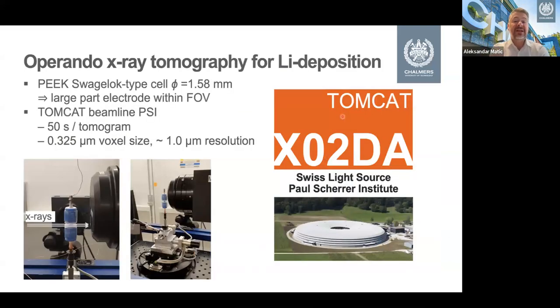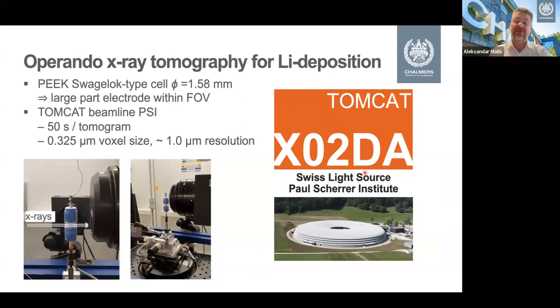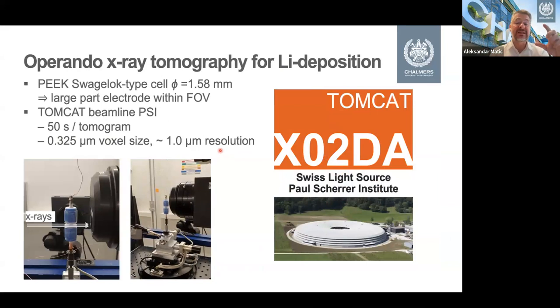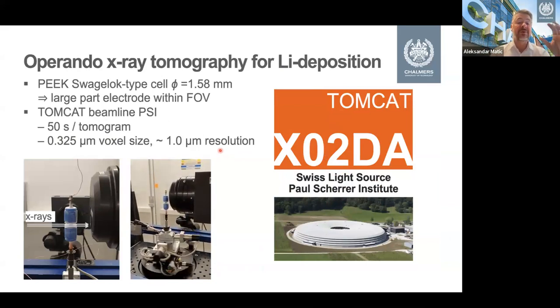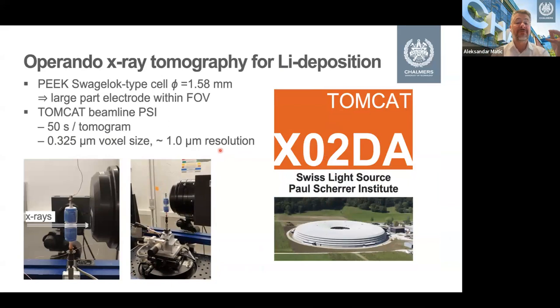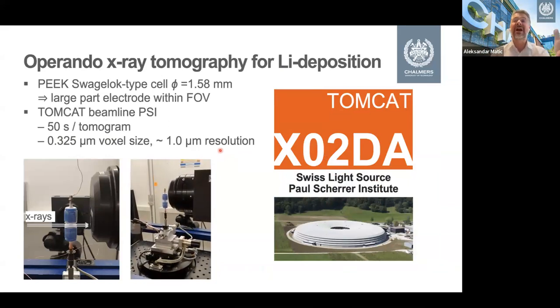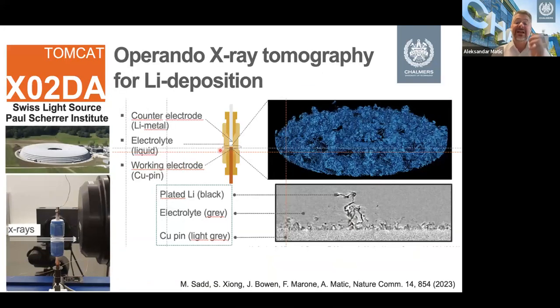And many people say that, oh, lithium is not good for X-rays because it's a light metal. You cannot see it. But actually, we proved the contrary in this experiment, which we did at the Swiss Light Source at the Paul Scherrer Institute at the Tomcat beamline. So with a specially designed electrochemical cell, we could measure a full 3D tomogram of a working battery in 50 seconds, with around a micrometer resolution. And here you can see the result where we have a copper electrode and we deposit lithium on top.